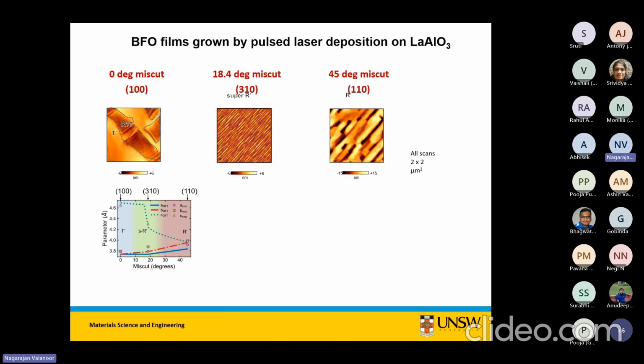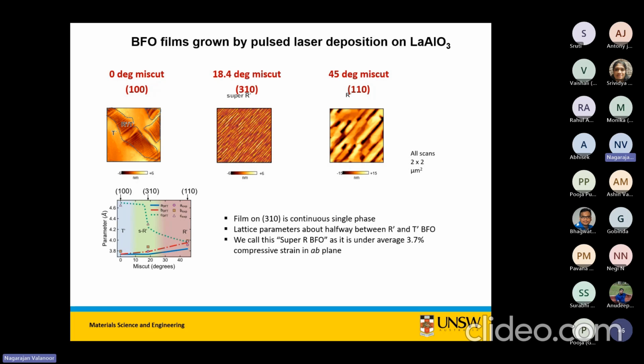Okay, and we call this phase the super R phase, the super rhombohedral, because it's not really tetragonal, it's not really monoclinic, it's not really rhombohedral. It's actually a rhombohedral phase that is under 3.7 percent compressive strain anisotropically in the AB plane. So there's a very complex crystallographic state where along one axis it is allowed to relax the strain by dislocation formation, and along the other axis it is not allowed, it has to tilt. The net result is that you get a new crystallographic phase of this ferrite with a tilted polarization. Now, if you're familiar with piezoelectricity, tilted polarization is great news because when you apply bias, you can rotate it, and you get a large piezoelectric coefficient. So that played very well into our idea, right?